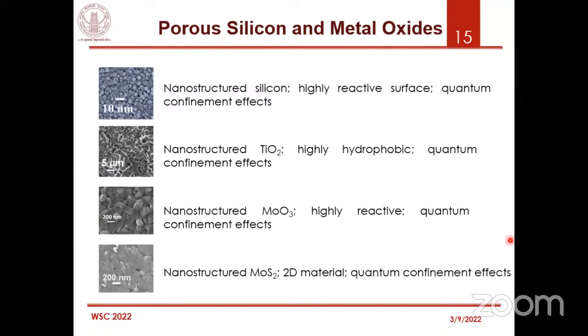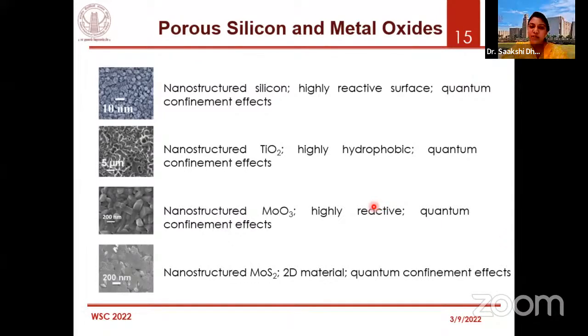Okay, thank you. So if we club this metal oxide with porous silicon, what we observed is that the operating temperature of this sensor went drastically down to room temperature, mainly because of these two junctions, right? One coming from porous silicon and the other coming from metal oxide, right? Both being semiconductors. So once they form this NP, PN or PP plus junction, the depletion layer that is formed in between these two junctions helps us to get sensing results at room temperature, right? So nanostructured silicon, we also call it porous silicon.